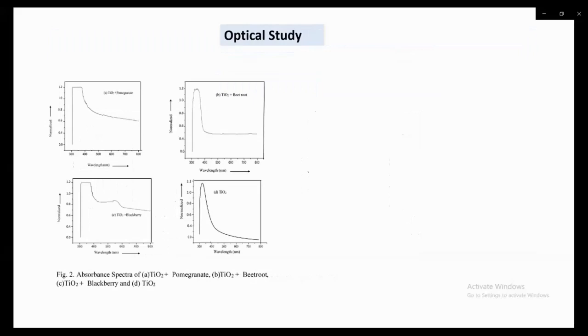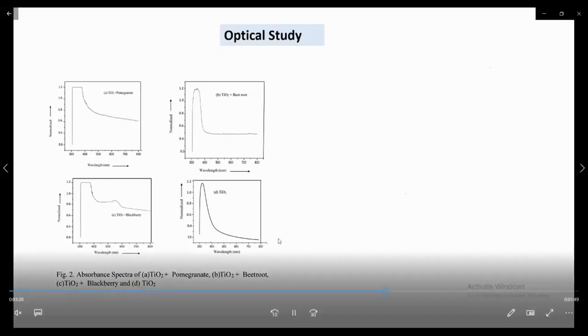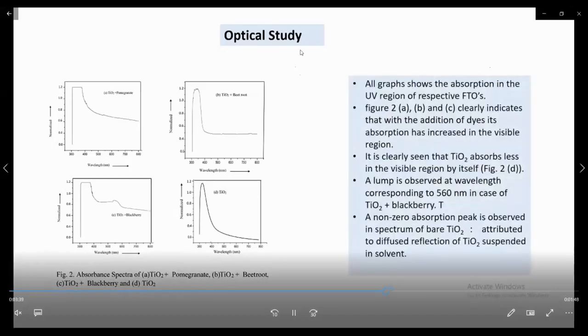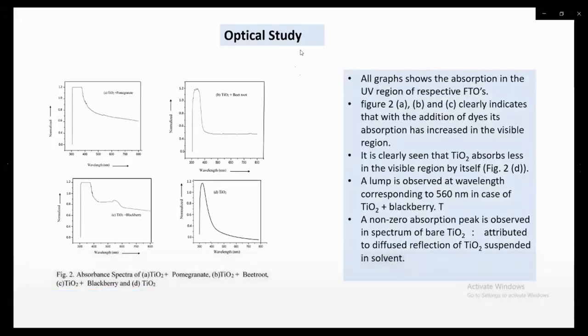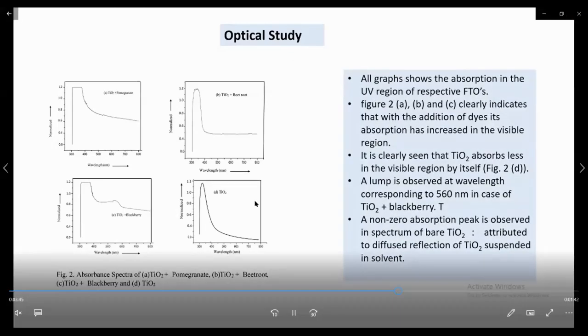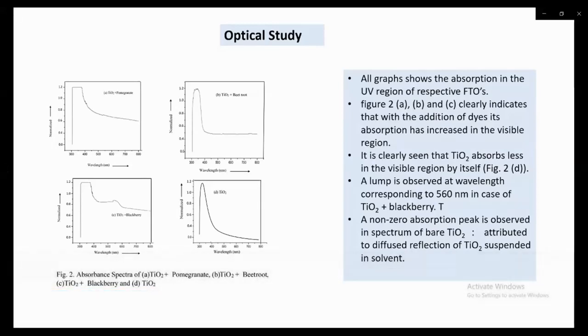Now for optical study, we can see the absorption spectra of TiO2 plus pomegranate, TiO2 plus beetroot, TiO2 plus blackberry and the bare TiO2. So from this optical study, one can see that all graphs show the absorption in the UV region of respective FTOs. If we see figure 2A, B and C clearly, it indicates that with the addition of these dyes, its absorption has been increased in the visible region.